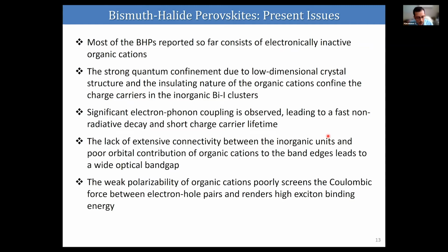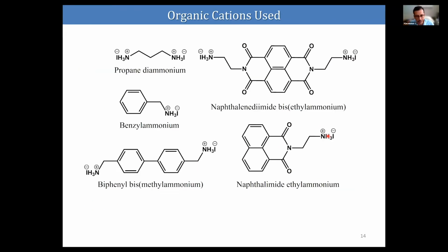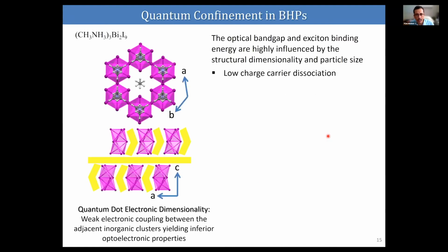So we are trying to address these issues, how we can try to address these issues, whether it is possible to address this issue. And we selected a few organic cations to develop bismuth halide perovskite and see how it is performing in the perovskite structure. First, we try to understand the quantum confinement in this material, and because of the high quantum confinement in this material, they show very high exciton binding energy and low charge carrier dissociation.